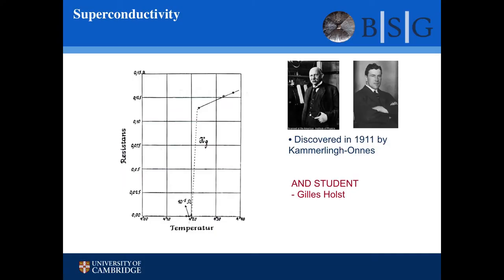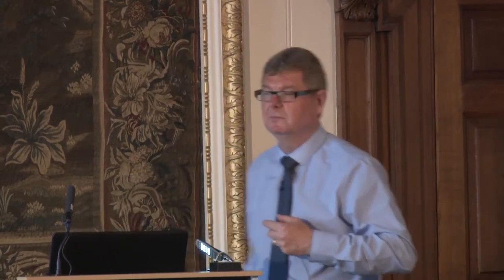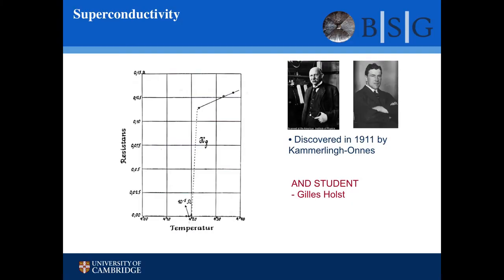So here's Kamerlingh Onnes looking very grand in his laboratory in Leiden. And here's the plot. It's the resistivity of mercury versus temperature. And down it trundles this nice linear slope. And there were various predictions about what happened at lower temperatures. So some people thought it just continued to decrease linearly. Others thought the resistance leveled off. And that's quite insightful, some kind of limited lattice vibration mediated scattering, which gives you this fundamental resistance. Lord Kelvin, for some reason, predicted that it would increase again. Nobody quite understood why he predicted that, but he did. Nobody, however, predicted that the resistance would disappear completely.